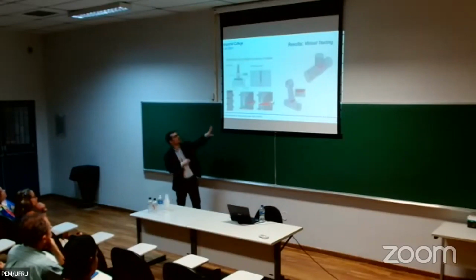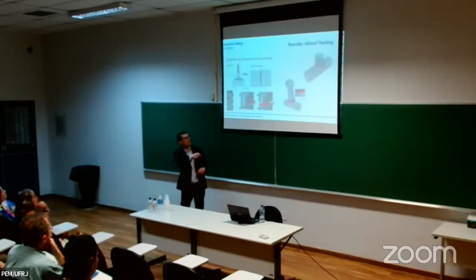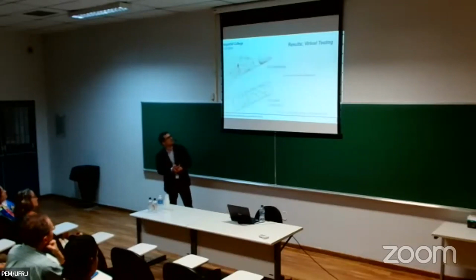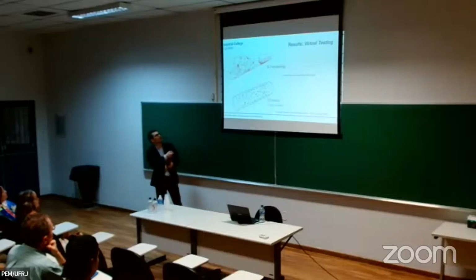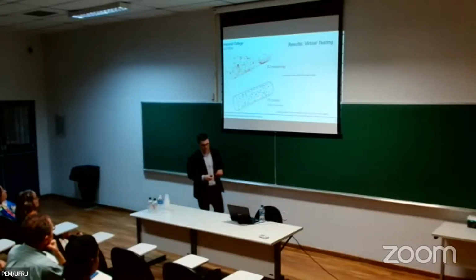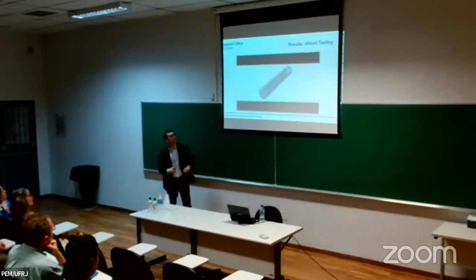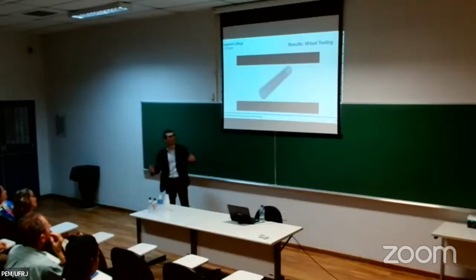We can simulate standardized lab experiments in our computers, but we can also deliver predictions for large scale engineering practice, so we can handle technologically relevant large scale 3D problems, as you can see here. And more excitingly, we can also couple this with inspection, creating a sort of digital twin of critical infrastructure. What you see here is a 12-kilometer pipeline characterized by inspection, and all these red dots here are pits, defects originating from pit corrosion. So we decided to model a critical section of 3 meters that contains more than 100 of those defects, and then we can subject our pipeline to in-service conditions in the computer, and we can see how those defects are growing, how they merge, and how they evolve over time. You can see here at the top, they start to merge, they coalesce into other defects, and then eventually we get the failure of the pipeline.